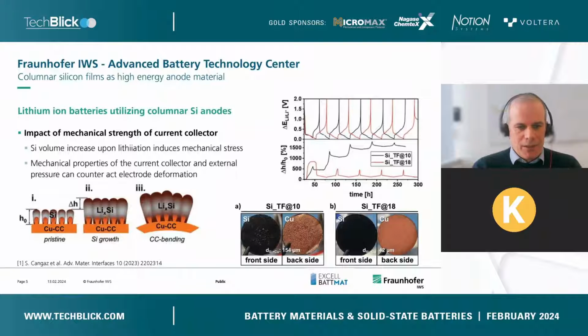The main challenge of silicon, as we mentioned today already, is volume expansion upon lithiation. This is also happening in our films, and this induces a high stress in our films. And we spent quite some work on identifying possible solutions or compensation for this stress induced during lithiation. We worked on microstructuring these films, but also on the role of the substrate, and this is shown here on the photographs on the bottom right.